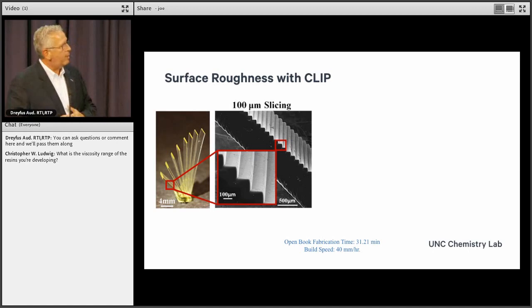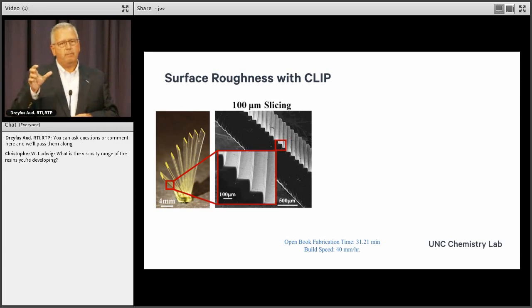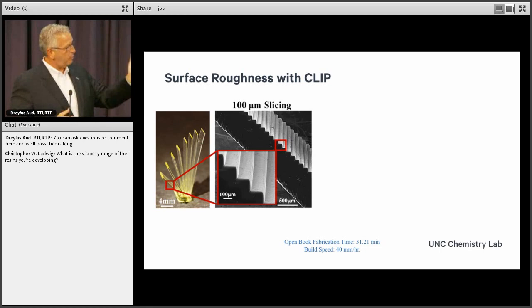So this is an example from one of my students at UNC, and this is Rima's work. She was growing parts, and it had a particular angle with this part, and what she was doing is she was holding the image constant, a slice, an increment of the image constant, while the part was growing, and in every 100 microns in Z, she would change the image. Hold it constant, grow it, change the image, every 100 microns in Z. And so something that you'd expect to be smooth is staircased because she was holding it at 100 microns in vertical while it was going and then switching.